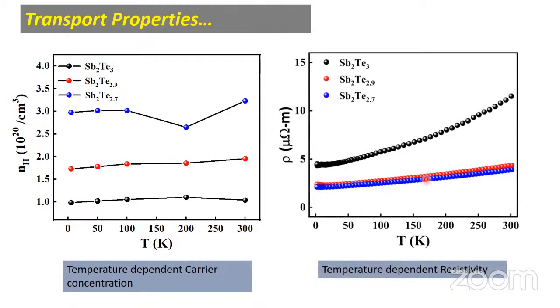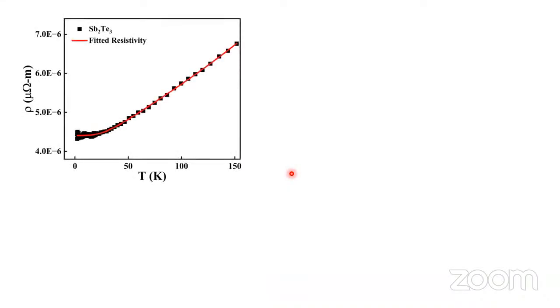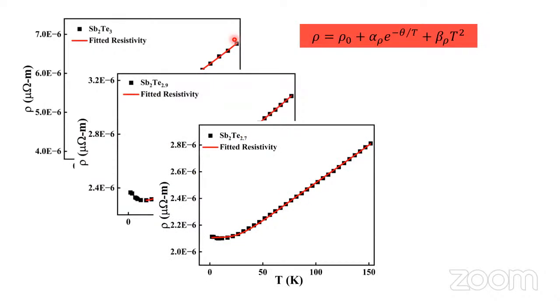And this is the temperature dependent resistivity data. Resistivity is drastically decreased with increasing tellurium vacancy. This is consistent with the NH data. Now, all the temperature dependent resistivity data are fitted with a well known equation.